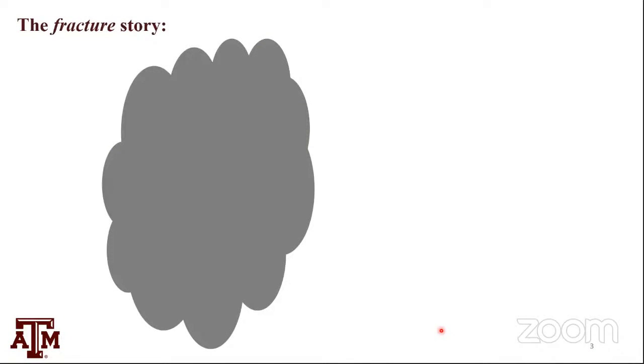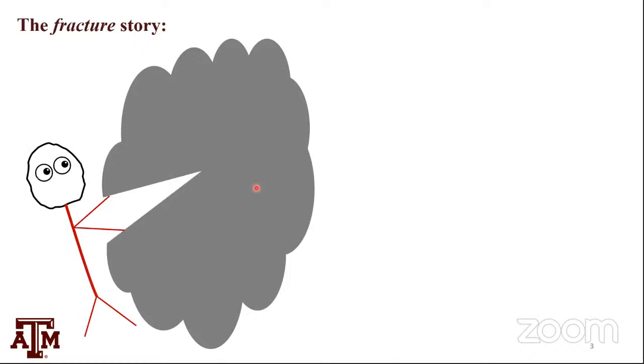So, a simple fracture story. Let's consider a blob of material. It's a piece of gray metal, let's assume, or any material that has a crack in it. Fracture mechanics basically says I've got a bad guy, the driver, trying to open the crack, and I have a good guy sitting inside the material trying to resist the crack growth. In Star Wars terminology, I've got the emperor and I've got the resistance. As long as the bad guy loses and the good guy wins, the crack stays where it is. Once the good guy loses, the bad guy wins, and the crack starts to grow. It's a pretty simple story.